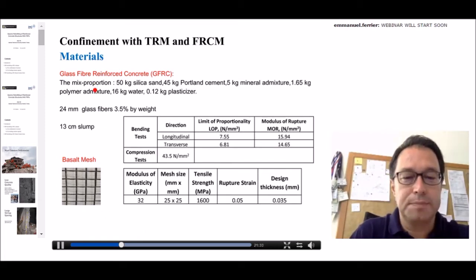Some information about the materials that we used. If you look at glass fiber reinforced concrete, this has a flexural tensile strength about 15 megapascal and compression strength of 44 megapascal. And if you look at basalt mesh, this has the mesh size of 25 millimeters in two directions. Elastic modulus 32 gigapascal. Quite high rupture strain, about 5%. And tensile strength is about 1,600 megapascal. I think I don't have that slide, but if we use it like a composite material with this GFRC and basalt mesh, we have some value of about 7 megapascal for tensile strength.